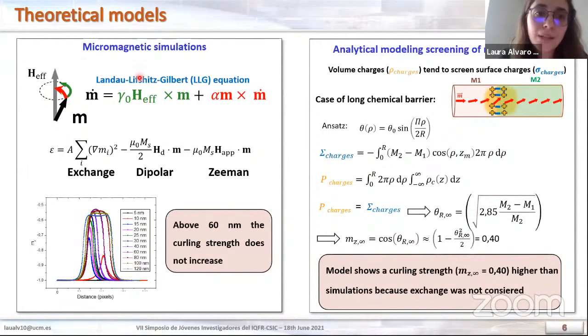So the first one is in micromagnetic simulations, where we observe that the curling has a limit because as we increase the size of the modulation, this curling increases, but there is a point that occurs at 60 nanometers where it reaches a plateau. So then we see that there is a limit in the curling.